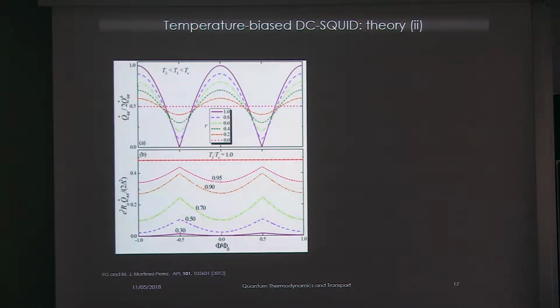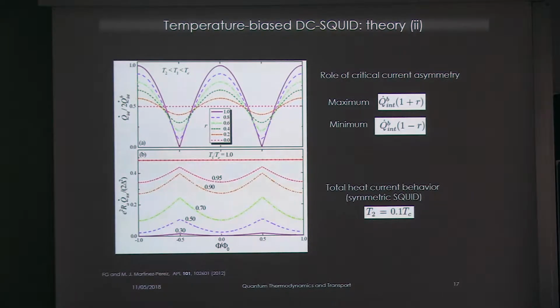Then if we look at the full heat current, the quasi-particle plus the phase-dependent part, it has a quite complicated behavior in general because at low temperature it is almost vanishingly small, and to achieve a sufficiently large heat current you have to create a larger gradient in the system. So typically you have to go into the nonlinear regime of the system in terms of temperatures.